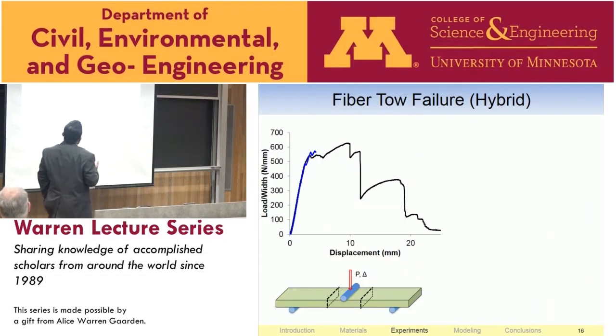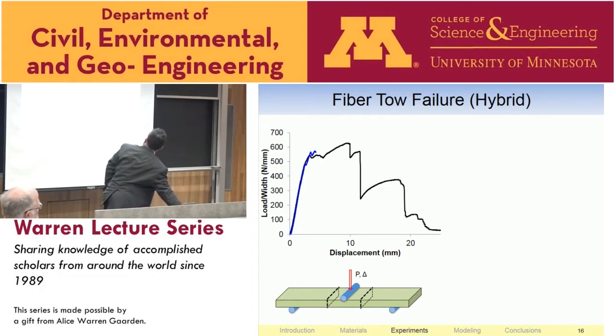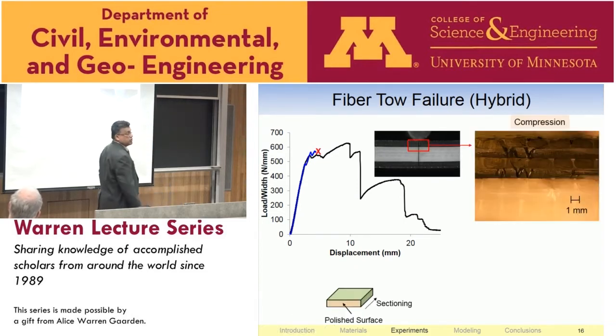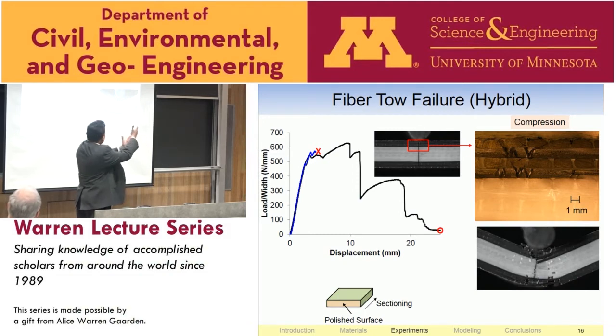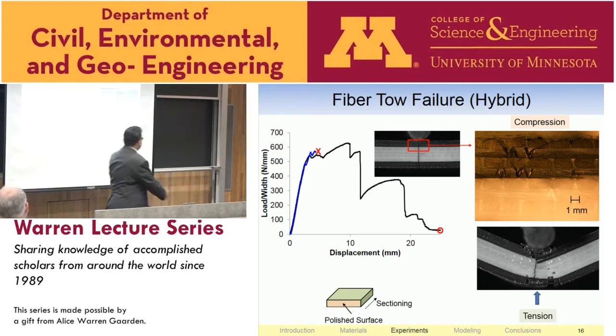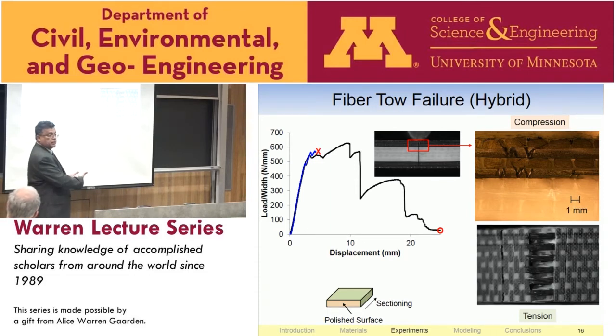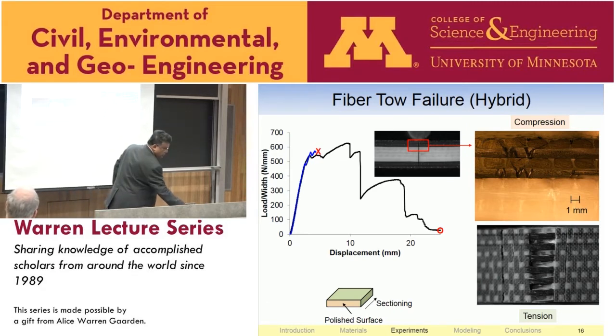So here I'm showing also how the fiber tows fail. You can see that it kinks there, and then if I start looking at it closer and closer, you'll see the progressive kinking, the shear bands that form in those layers, and the bands keep transferring load, and you get another shear band, and another shear band, or we call it a kink band, and it continues to grow. But that's good. It's contained, and therefore it's dissipating energy, but in a localized zone. And so final collapse occurs when the bottom tows in the structure fail in tension, tensile failure in the carbon tows.